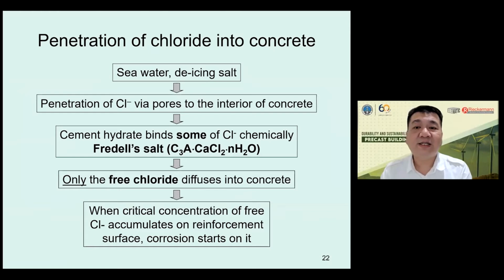Now, another degradation is the chloride penetration into the concrete. And the chloride source normally is from the seawater or de-icing salt. So chloride is actually a very deteriorating agent in the steel. So we have steel structures also, and we also have the reinforced concrete. When exposed to seawater, the degradation normally is very fast due to the chloride effect in the process. So the chloride diffuses into the concrete, and when the critical concentration accumulates at the reinforcement, the corrosion will start.